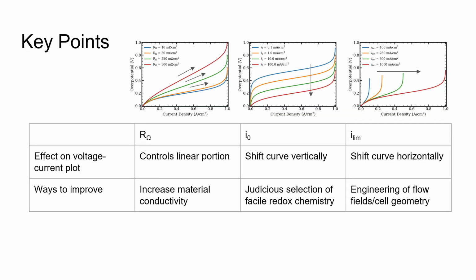To summarize, let's go over each effect on current voltage relations and how to improve them. Ohmic resistance, which controls the linear portion of the curve, can be reduced through increasing material conductivity, which can be done by adding a supporting electrolyte. For exchange current density, which shifts the profiles vertically, you can work with materials with faster kinetics, or consider catalysts. Lastly, with limiting current, which shifts curves horizontally, consider careful engineering or operational options like flow rate or paths in a flow battery, or electrode separation distance in a solid battery.